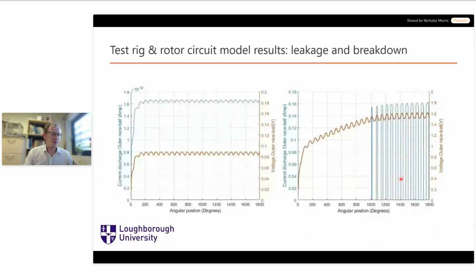And this is just to show some of the correlation between the model results that we can see, which we're not able to measure easily experimentally. So on the left-hand side is the condition when we haven't exceeded the dielectric strength of the lubricant with sufficient voltage. So we can see that we get very low current. The blue line shows the current passing through the contact. So this is the static dissipative behavior. So we get extremely low, this is times 10 to the minus 12 amps. And we have the voltage across the contact on the right-hand side here.